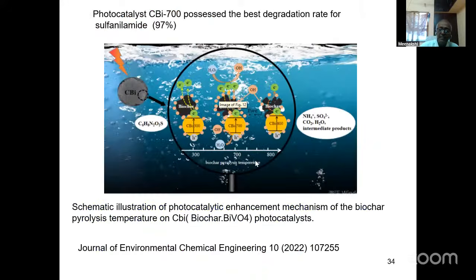And similarly, they have prepared biochar bismuth vanadate here. You can see CBi at three different temperatures. See here how the temperature affects. One is prepared at 300 degrees, another at 700 degrees, another at 800 degrees. They found that CBI 700 possesses the best degradation of sulfanilamide. It's a toxic chemical. So sulfanilamide degradation using biochar with bismuth prepared at 700 degrees is found to be most efficient in degrading this sulfanilamide.